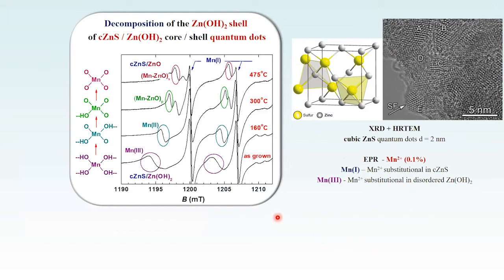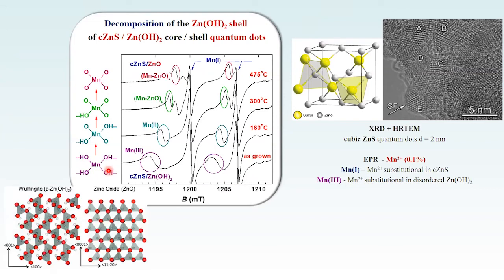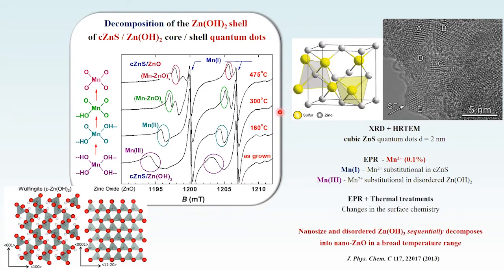We have two narrow lines from manganese ions in zinc sulfide, and then we have manganese ions in disordered zinc hydroxide at the surface, giving broader lines. The manganese coordination is noted: in these compounds the cations have tetrahedral coordination. By thermal treatment, we change the chemistry and observe by EPR a sequential decomposition of zinc hydroxide to zinc oxide.